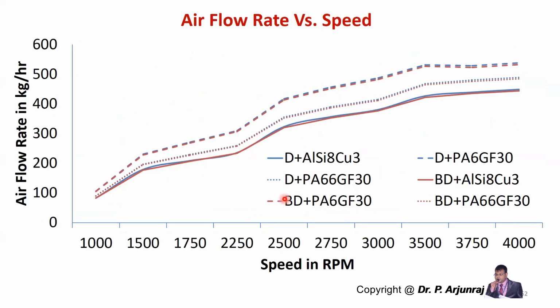And this is the airflow rate. The airflow rate is also high for diesel with PA6 glass fiber 30, and in biodiesel also PA6 with glass fiber 30 has a higher airflow rate when compared to the other materials, PA66 glass fiber 30 and aluminum, at various speeds.